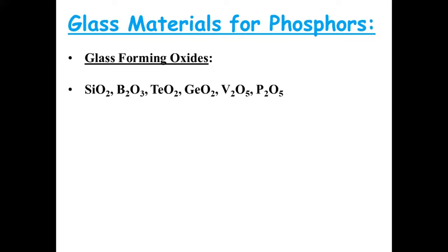So I will be discussing the fluorescent properties of glasses based upon tellurium dioxide. It's a special glass forming material. It does not form glasses easily, but when you add sodium oxide, calcium oxide, heavy metal oxides like bismuth oxide or tungsten oxide or copper oxide to tellurium dioxide, it forms glasses very easily, and its melting point is also low. Melting temperature of tellurite glasses based on tellurium dioxide is about 800 to 900 degrees Celsius.